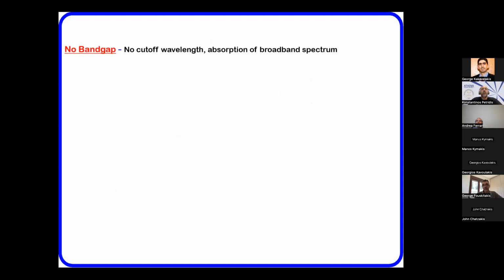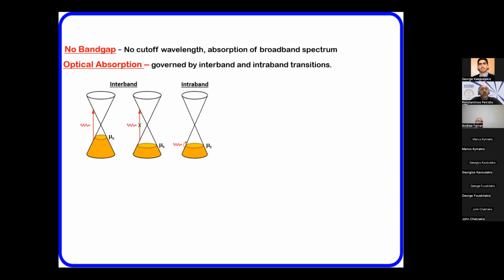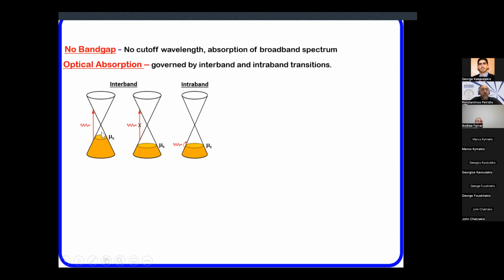So graphene is ideal for optical communication because it doesn't have any bandgap. So it works at any wavelength, any frequency we want. And the optical absorption in the simplest approach is basically as shown here. If you have a piece of graphene that is doped to a certain level, if your energy of light is larger than the doping level, or twice the doping level, you are able to excite an electron hole pair, so the light is absorbed. If it's not, you are not able to excite. And this would be the basic principle of light modulation.